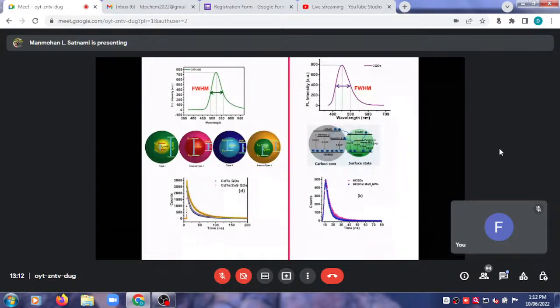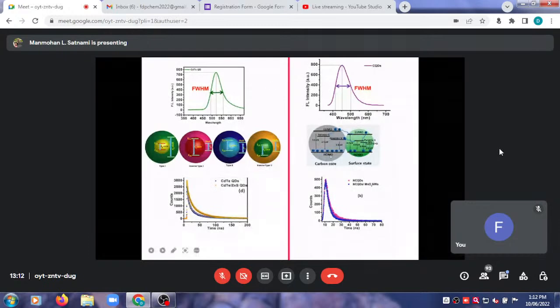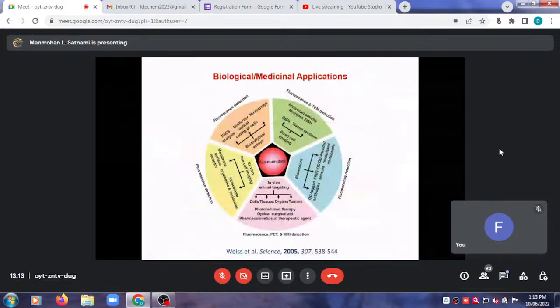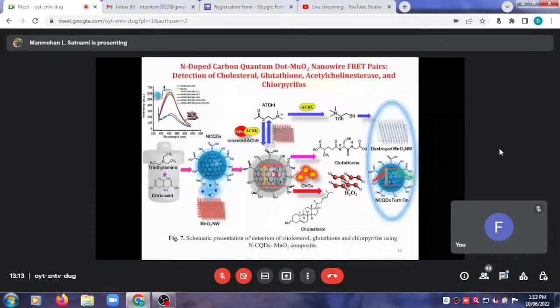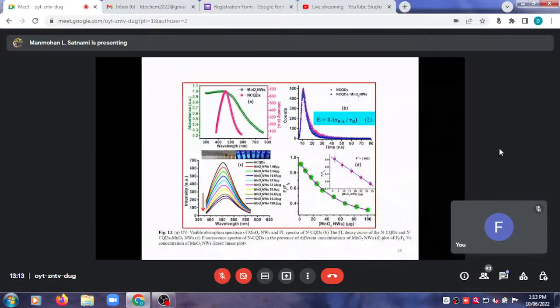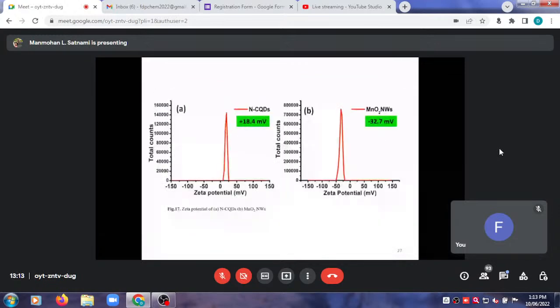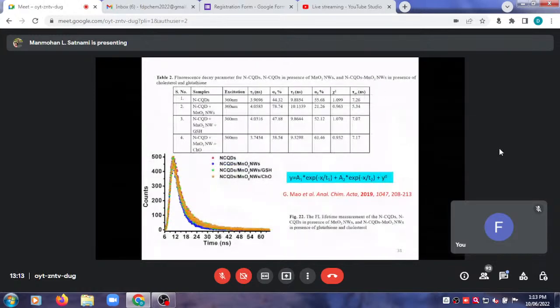And other than this, if there is pyridinic, amine-like nitrogen, then there will be different energy states in the same carbon quantum dot. Now think, if we excite this carbon quantum dot with UV light, the electron will go to the LUMO. When it comes back to the ground state, it can directly come back to the HOMO, giving fluorescence, but before coming to the ground state, it can go through different energy states, like graphitic, pyridinic, amidic. Then the fluorescence will shift towards higher wavelength, because the energy gap between this pyridinic state and the LUMO is decreasing. So on the basis of these kinds of nitrogen doping, we can interpret the different types of fluorescence emission of carbon quantum dots.